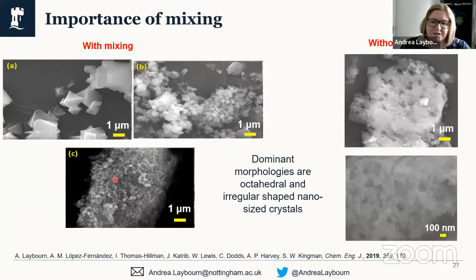Now, I mentioned a couple of minutes ago that mixing is really important. And so I want to demonstrate that with this particular example. So when we were mixing our materials using the oscillatory baffled reactor, we were typically getting octahedral morphologies from materials and then irregular shaped morphologies where we had many particles within our products where these particles had agglomerated together.